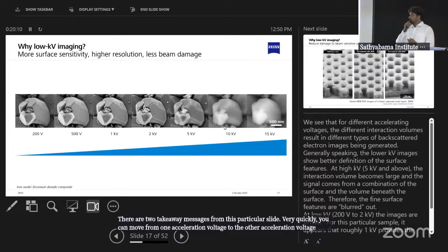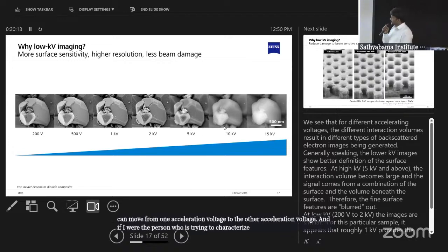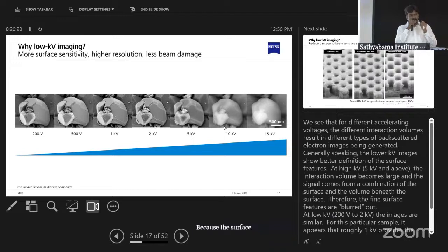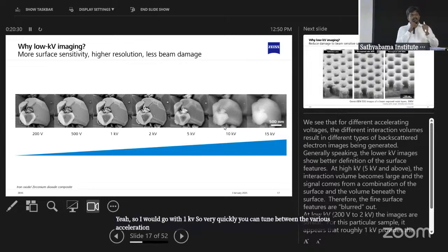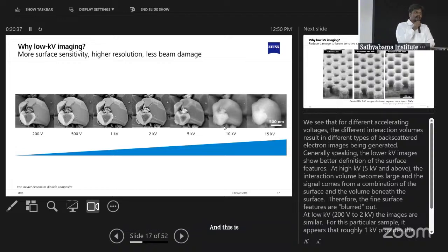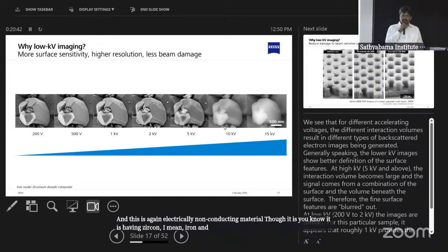And if I were the person trying to characterize, I would prefer maybe 1 kV or 2 kV. I would go with 1 kV because the surface details are very, very crystal clear and crisp. So very quickly, you can tune between the various acceleration voltages and pick and choose which acceleration voltage is ideal for your sample type. And this is again an electrically non-conducting material. Though it has iron and zirconium, the oxidation state doesn't allow it to be completely conductive.